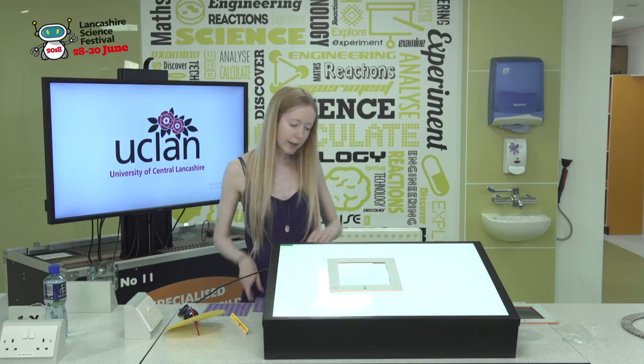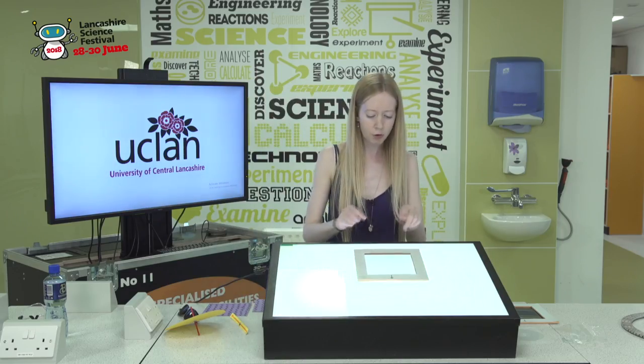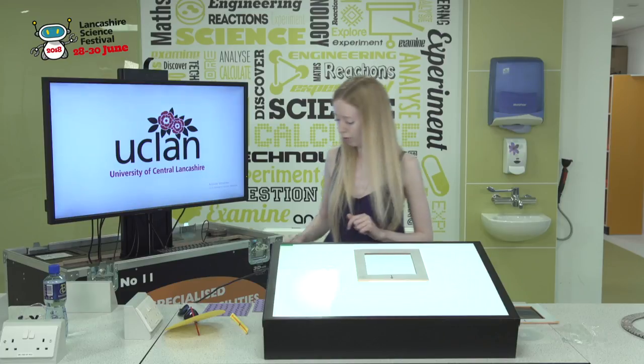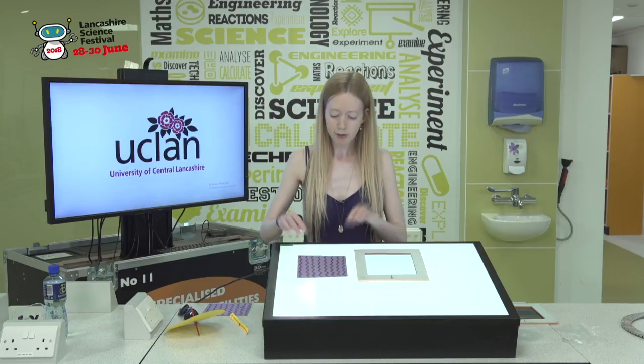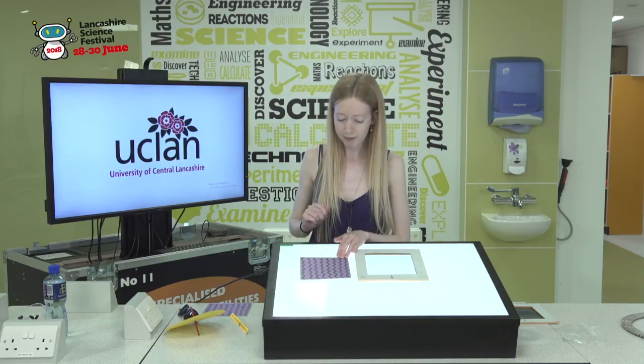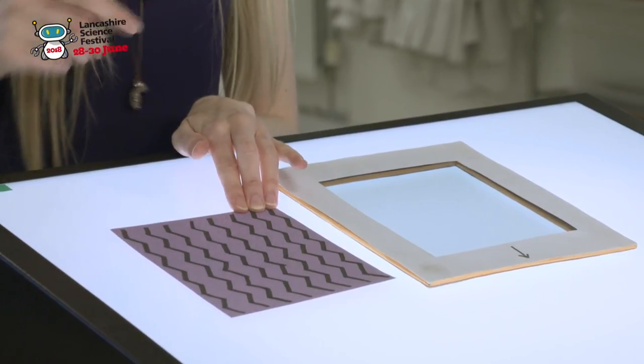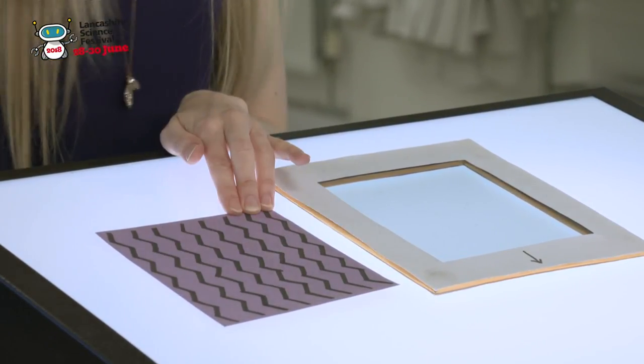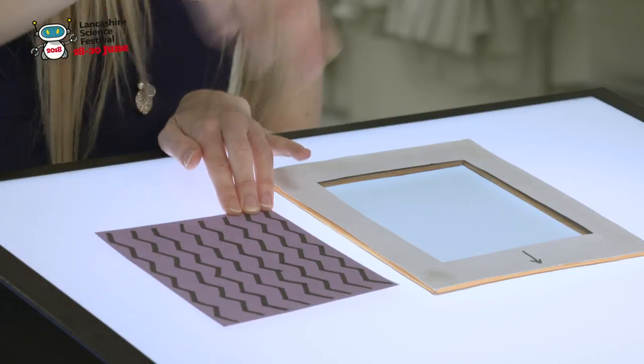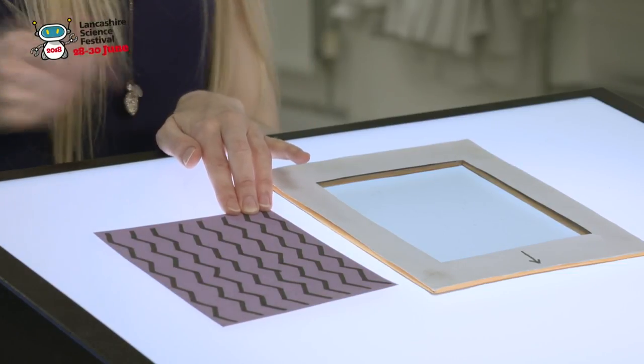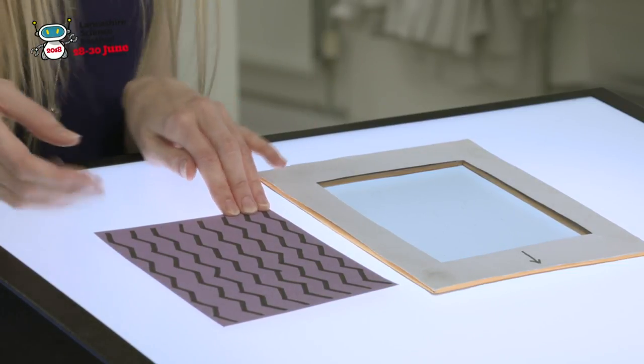So if you were to zoom in on this material, this polarizing filter, it would actually look something like this. So it's got these long chains in this polarizing filter. And these chains actually absorb the light along that direction and they let it through in the other direction. So that's how you end up with all the light in that one direction.